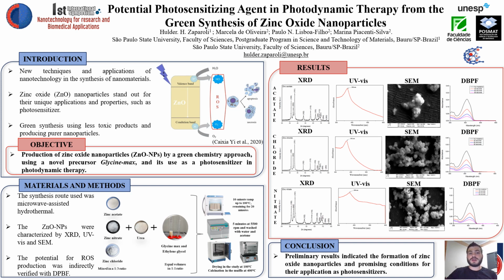The synthesis route used was microwave-assisted hydrothermal, and three different precursors were tested: zinc acetate, zinc chloride, and zinc nitrate. Each precursor was mixed with urea at a molar concentration of 1 to 3, and equal volumes of ethylene glycol and soy extract were added. After magnetic stirring, the solution was transferred to Teflon tubes and placed in a microwave digester with a 10-minute ramp until reaching the temperature of 100 degrees Celsius. After 20 minutes, the precipitate was collected, centrifuged, and washed several times with milli-Q water and acetone.